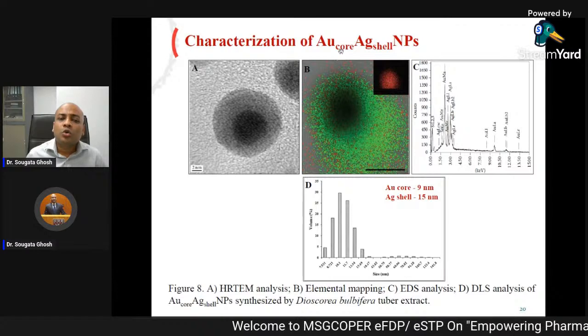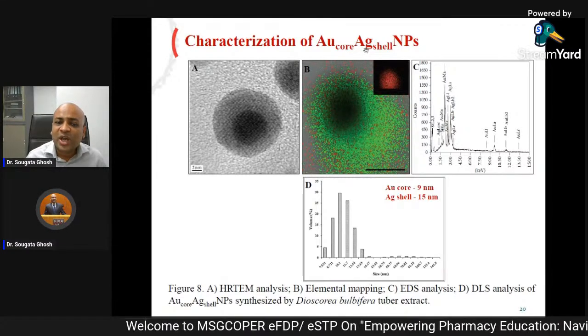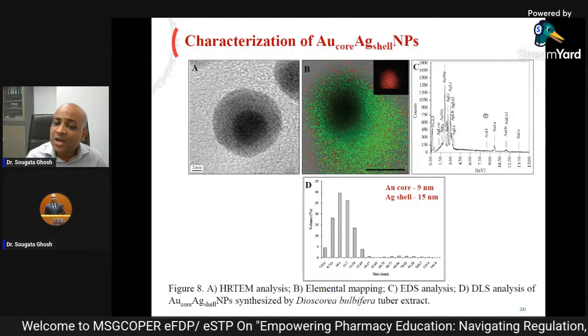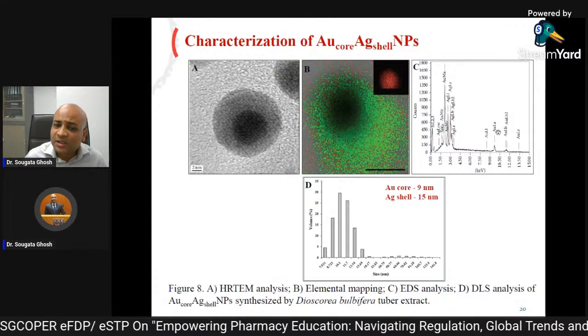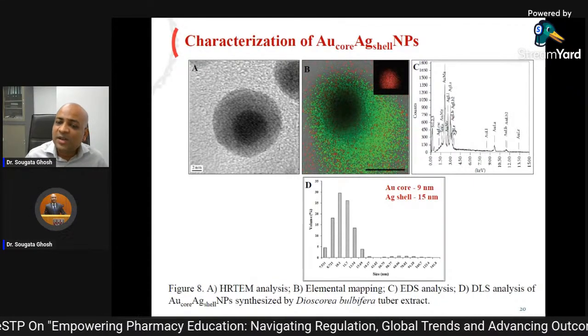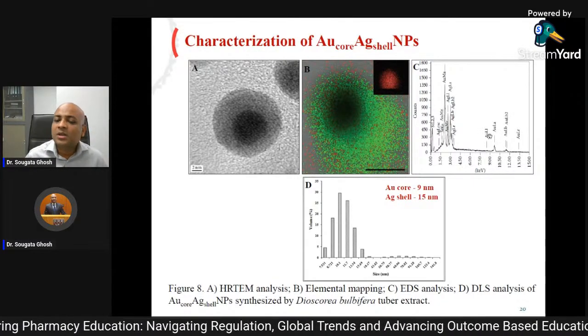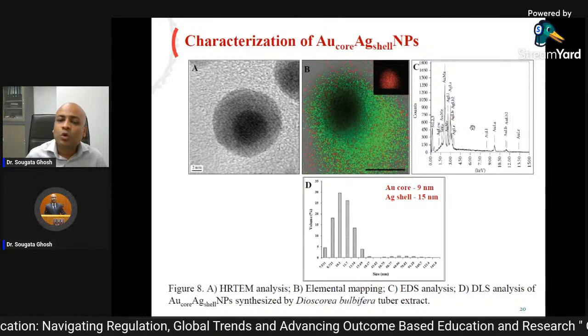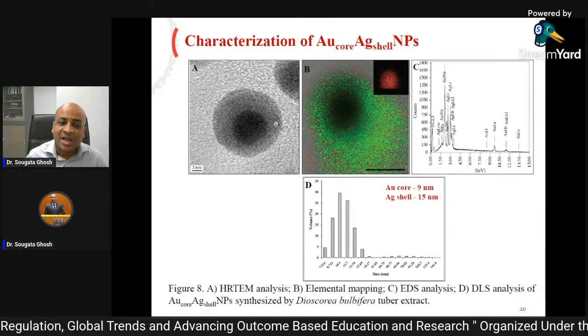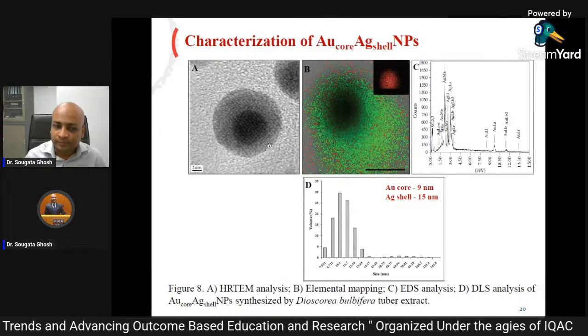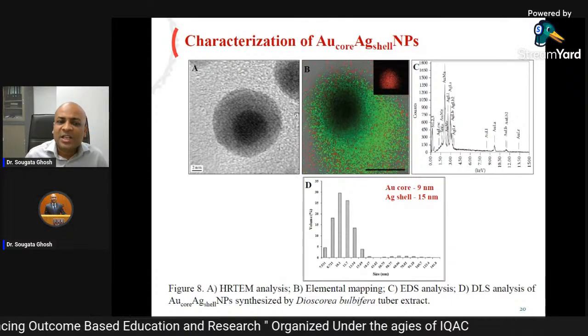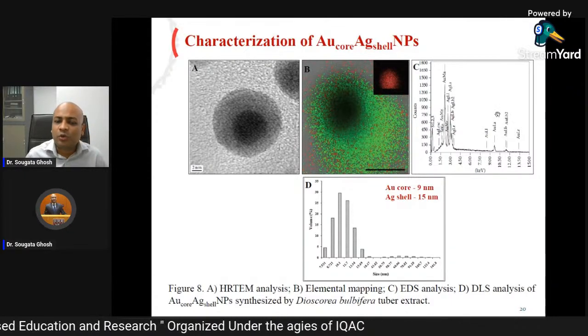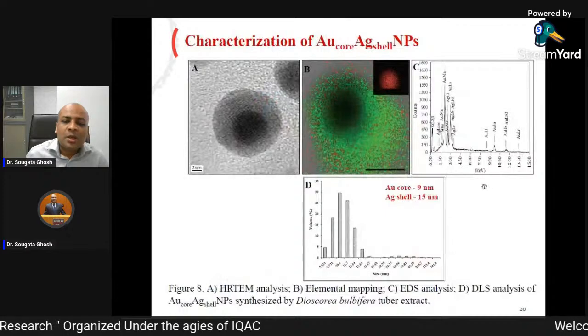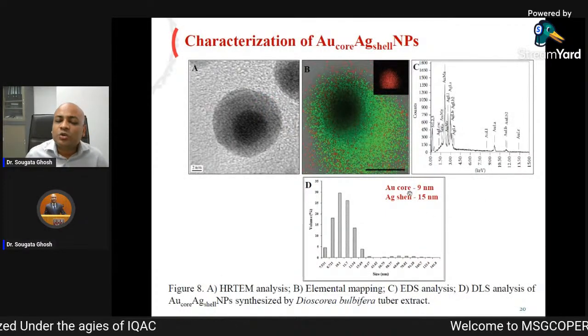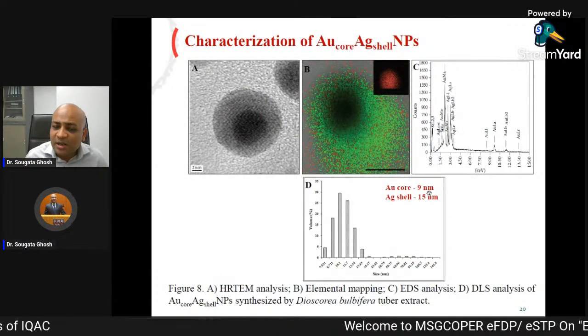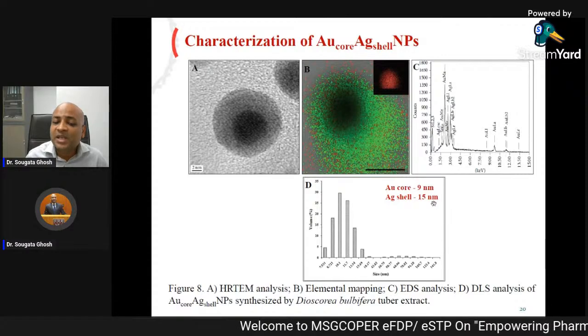So it is called a gold core silver shell nanoparticle. And we confirmed that with the help of EDS, it was silver that was present as well as gold that was present in this. So both gold and silver were present in the nanoparticle. It is like our 10 rupees coin. Gold inside, silver outside, like our 10 rupees coin. Right? So over here you can see this gold core was 9 nanometer and silver shell was 15 nanometer.